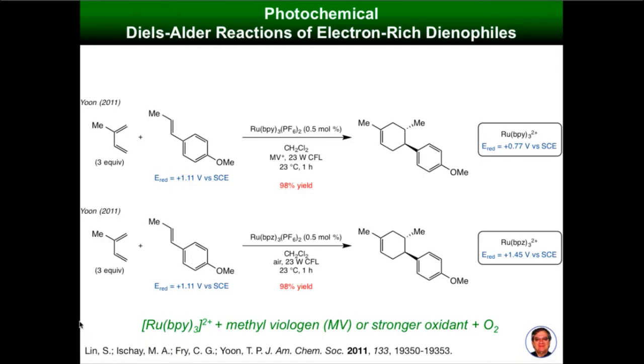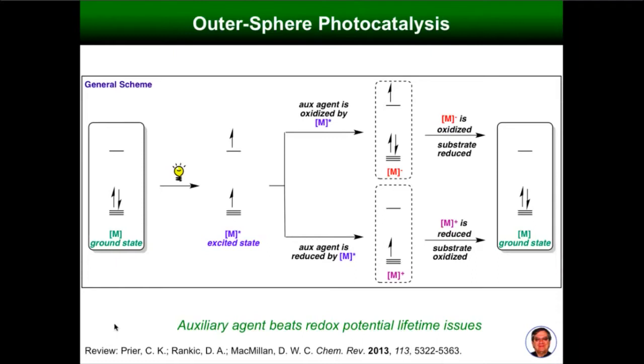They can get rid of that by increasing the oxidation potential of the metal species, but oxygen is a stoichiometric reagent in this case. So, reminding you that in general for these outer sphere processes, you have an auxiliary agent. Now that's okay in the pharmaceutical industry where you have small quantities, but if you're thinking about making gasoline, having a stoichiometric side reaction is probably not what you'd like. And so it'd be good to be able to get rid of this auxiliary agent.